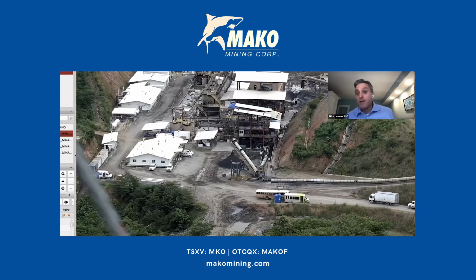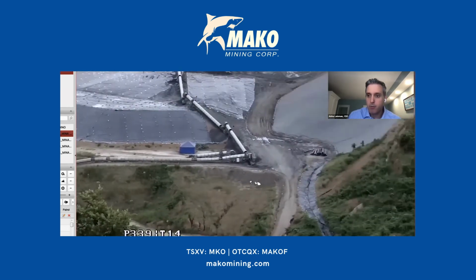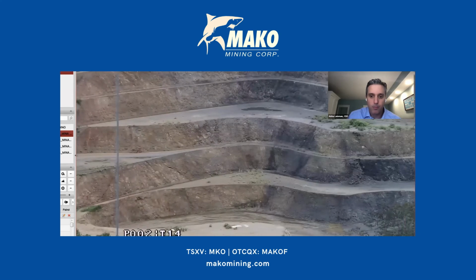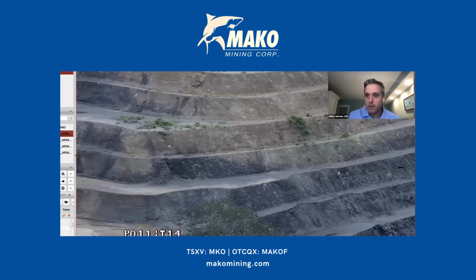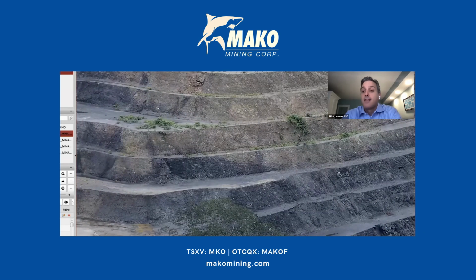So I have to say, even though this was expected, you can see it in the ore body. It goes from your lovely tan color mochaccino type ore body over there to that very dark black, you can see it obviously. So we knew about this happening, but there was a confluence of events that caused us to have that diminution of recovery. We implemented all of these processes and procedures on August 7th. It takes maybe about 48 hours of residence time over at our plant before you see any clear recovery change. And then really starting August 10th, our recoveries are back in line.